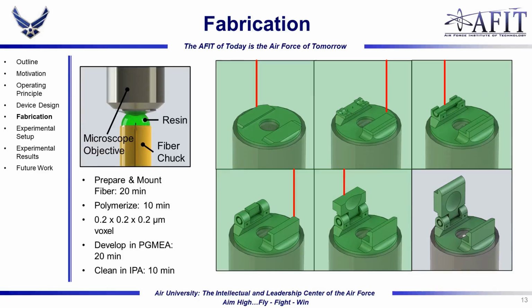This mounting process took about 20 minutes. Writing the device took about 10 minutes. You can see some of the layers as it was built up from the face of the fiber. You can see our voxel size there, that is in microns. After the device was written, the fiber was immersed into propylene glycol methyl ether acetate, or SU8 developer, for 20 minutes, and then cleaned off with isopropyl alcohol for 10 minutes.